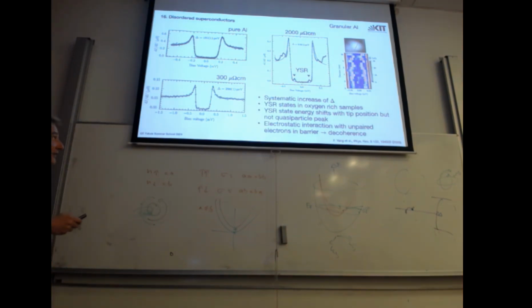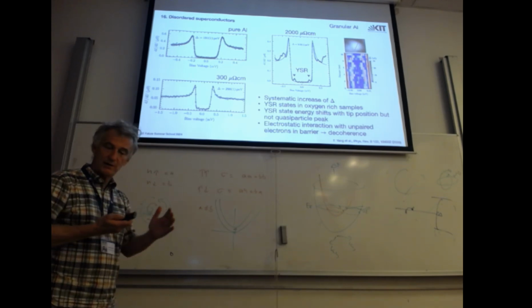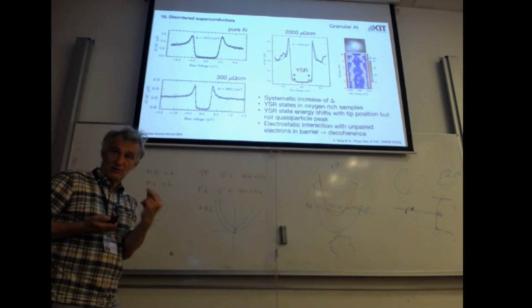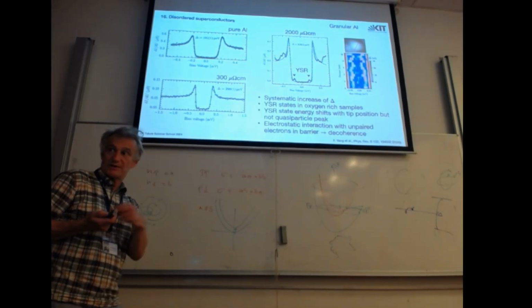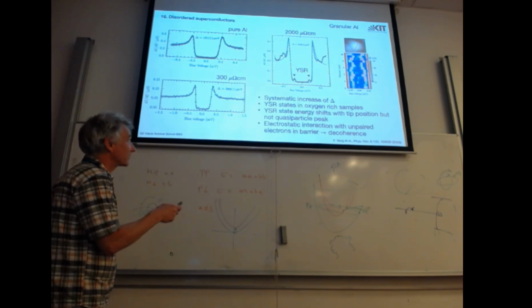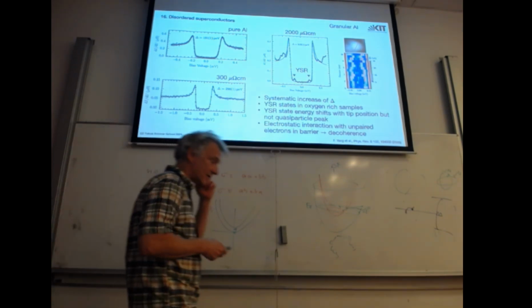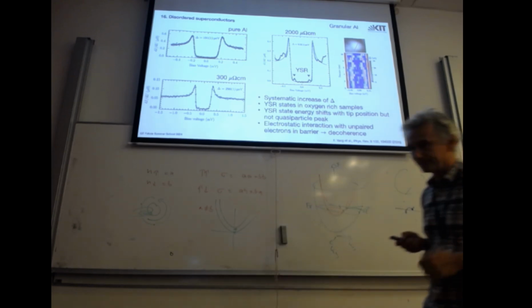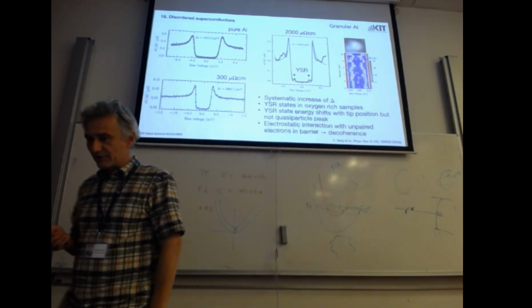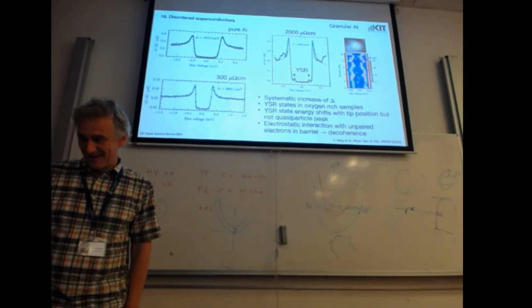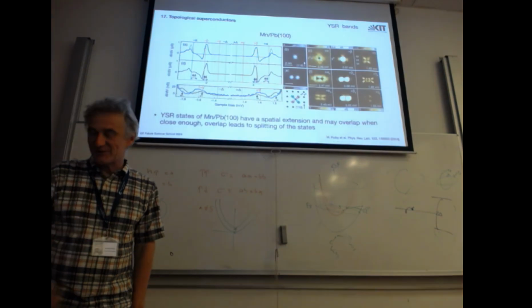So our belief is that in this oxidation process, we get amorphous aluminum oxide, and there are unpaired electrons there. If we separate the grains more and more, we have these localized spins which talk by tunneling to the superconductor and make these magnetic states here. And maybe this is the reason for the decoherence of this system. The decay is actually rather big. Jesus Christ, my time is over. So I have more prepared, and I will skip it.